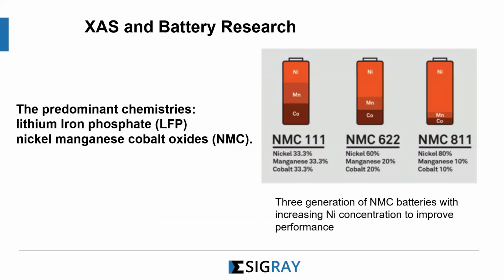We're going to show you some studies using the NMC type of material. The predominant chemistry in the commercial batteries is the lithium iron phosphates. But the one that is undergoing a lot of intense research is the NMC, or the nickel manganese cobalt combination. So NMC 111, or NMC 333, has 33% nickel, 33% manganese, and 33% cobalt.